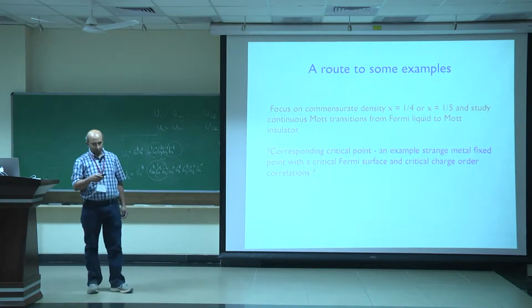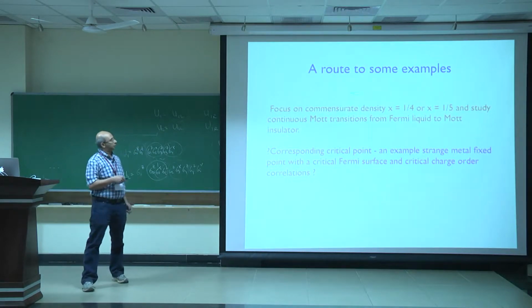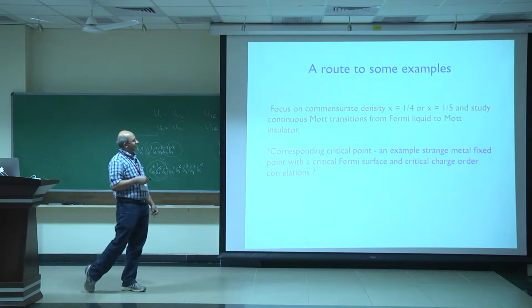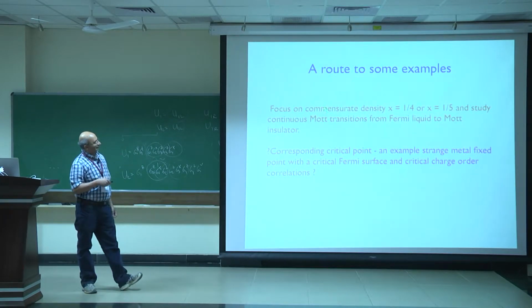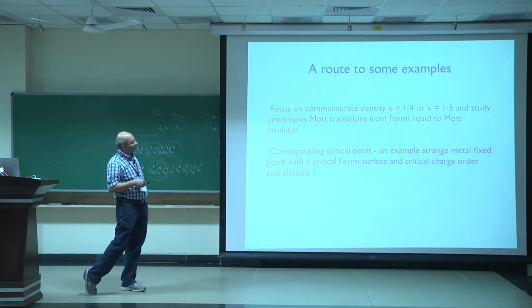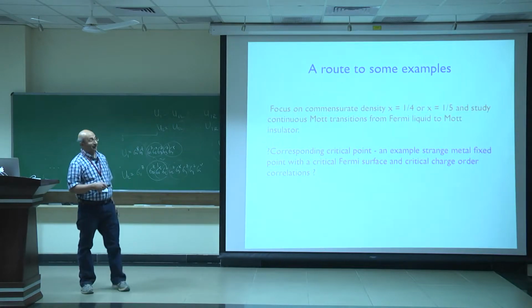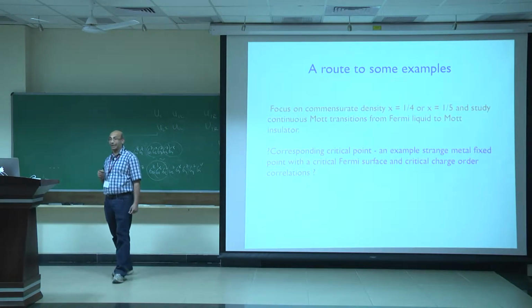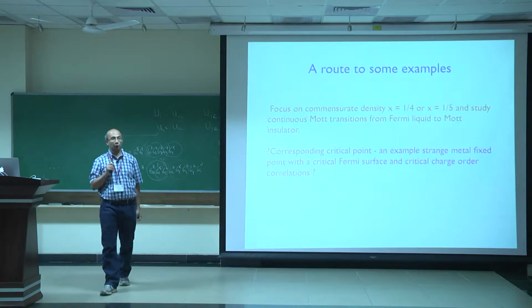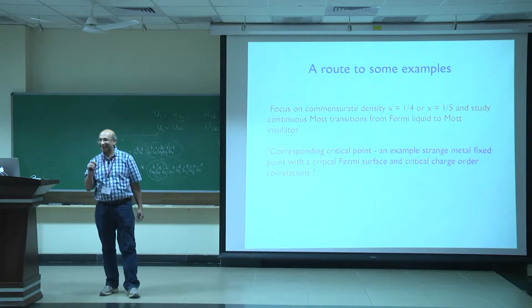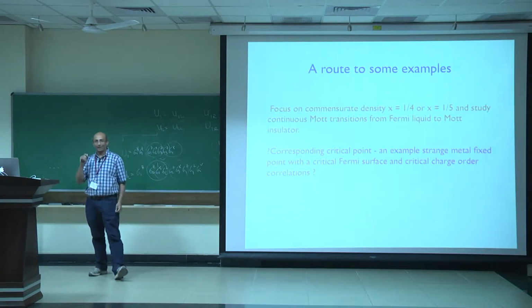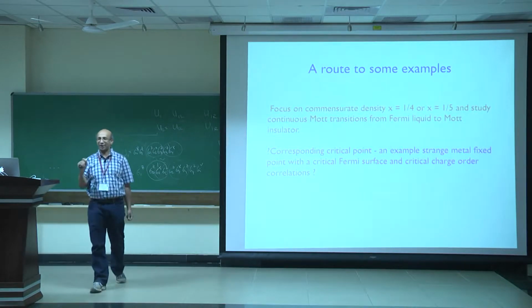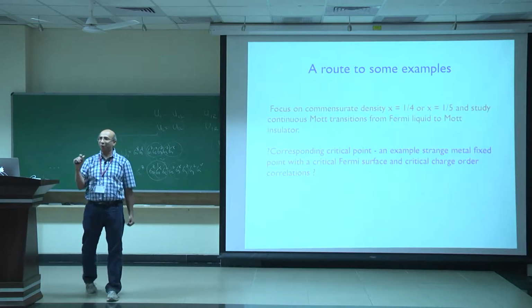So I'm going to take a route to constructing some examples of this kind by focusing on commensurate density, x is maybe a quarter or maybe 1/5. Actually, the initial spark for this project was the recognition that 19 is close to 20. Right? So 19% is close to 20%, and 20 is a simple rational fraction. It's 20%, it's 1/5.